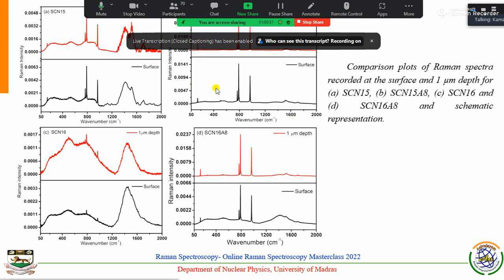So which means the damage is created at 1 micrometer, and even after annealing, recrystallization is induced at depth, but defects migrate towards the surface and accumulate there. So we can observe some small broad peaks at the surface, but not in the deep region. Similarly, we can observe in the SCN16 sample, the high dose sample, nothing is there.